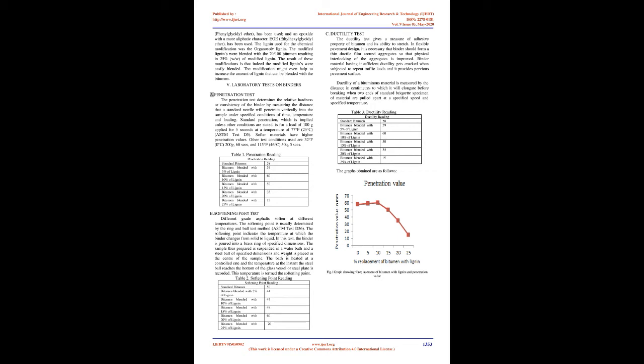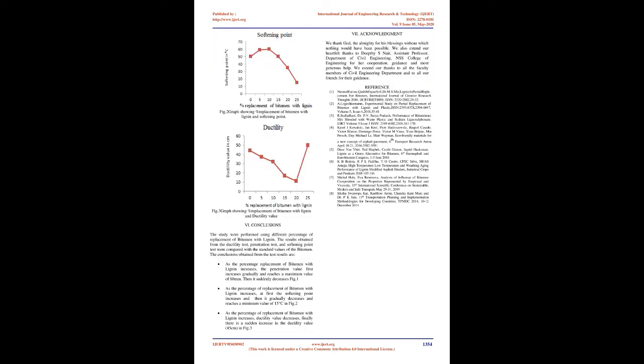The lignin used for the chemical modification was the organosolv lignin. The modified lignins were blended with the 70/100 bitumen, resulting in 25% w/w of modified lignin. The result of these modifications is that indeed the modified lignins were easily blended. The modification might even help to increase the amount of lignin that can be blended with the bitumen.